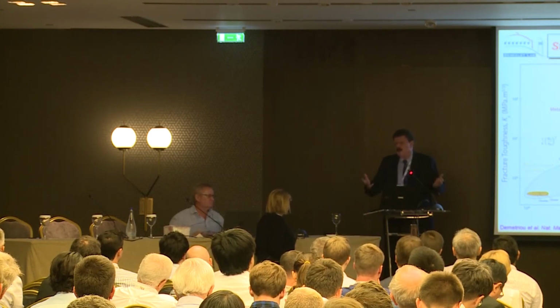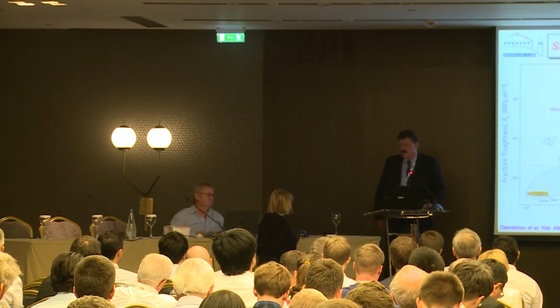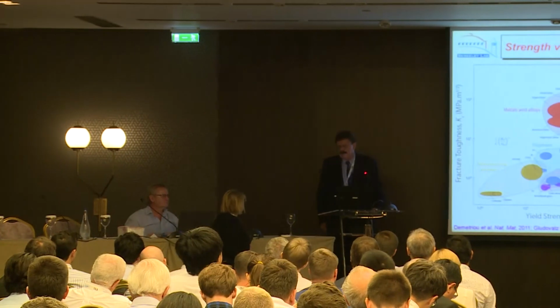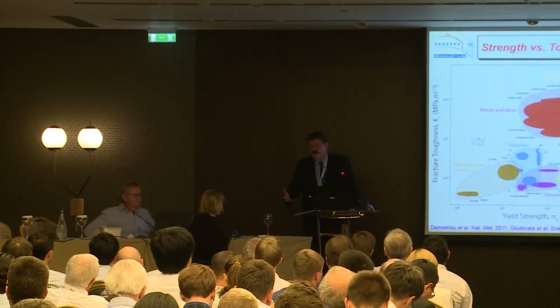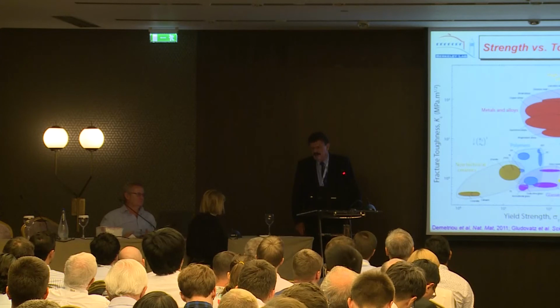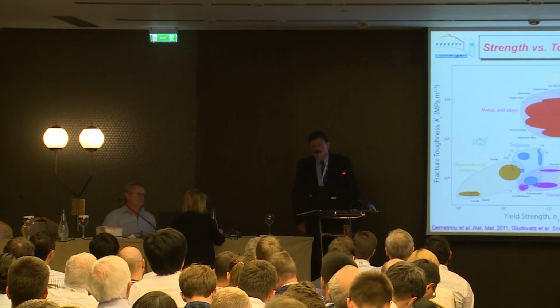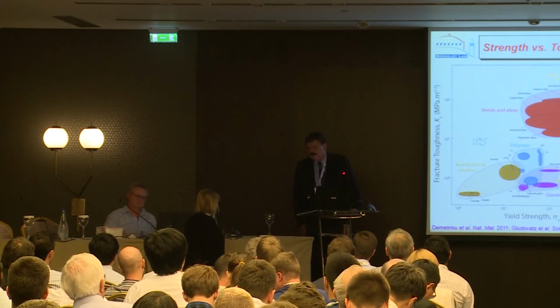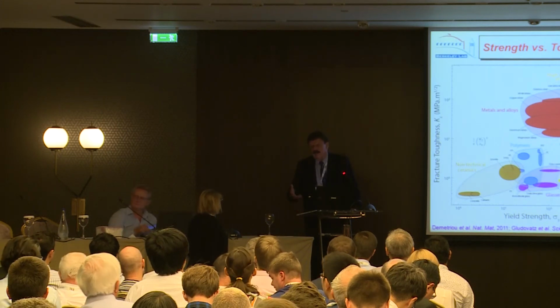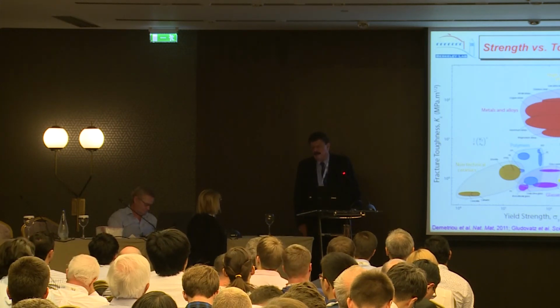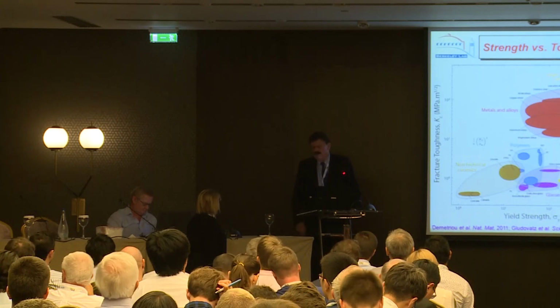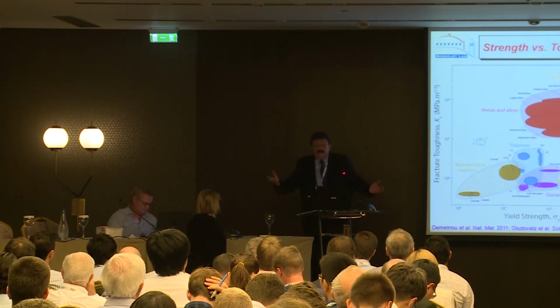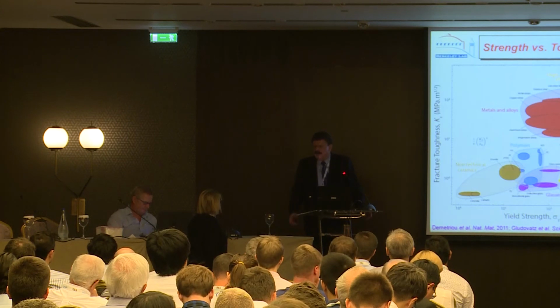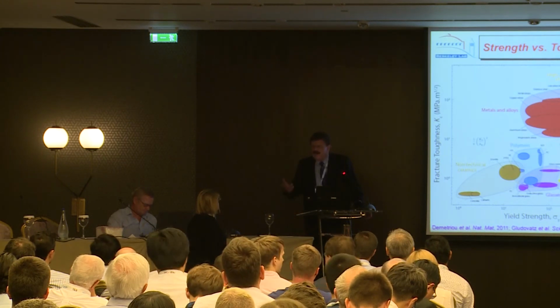But these high entropy alloys are relatively normal materials in terms of how you process them. You can make them in bulk. They're not little tiny bits of glass like the bulk metallic glasses are. So there's a very good chance they'll find a lot of applications. These have particularly good cryogenic properties, so they might be useful for tankage and pipelines. There's other people looking at high temperature versions of these alloys, not this composition. And of the 50 elements in the periodic table, there are 9 million of them out there,